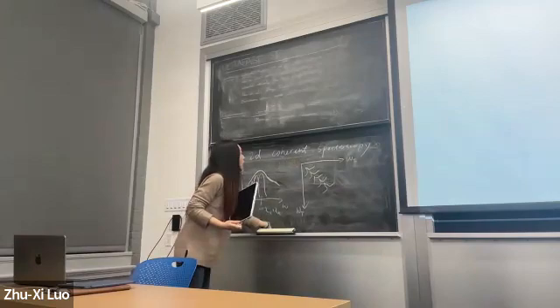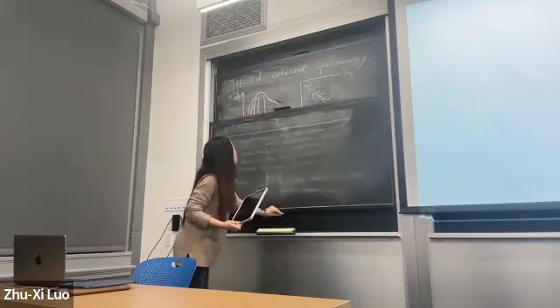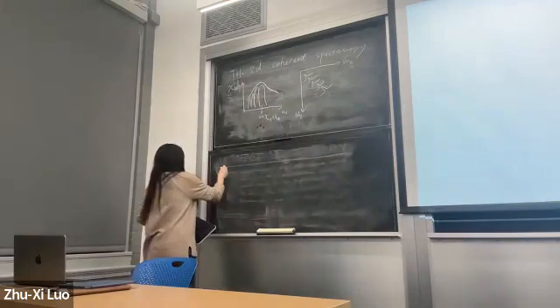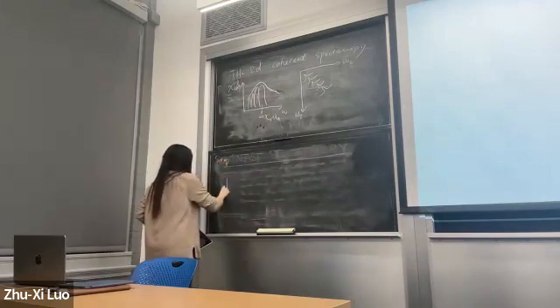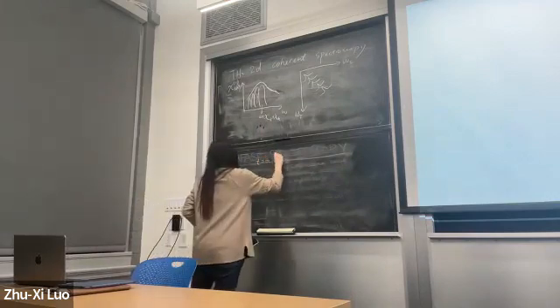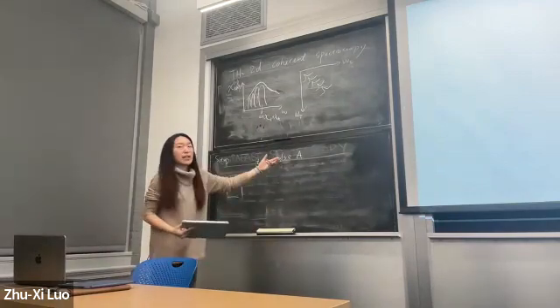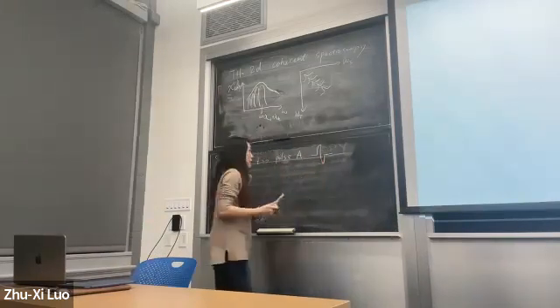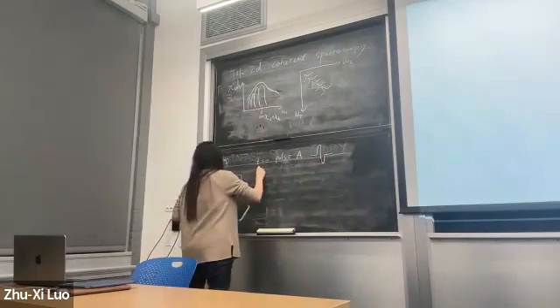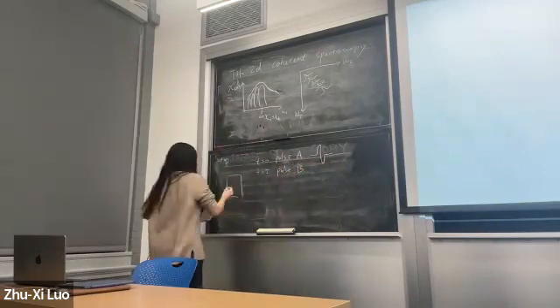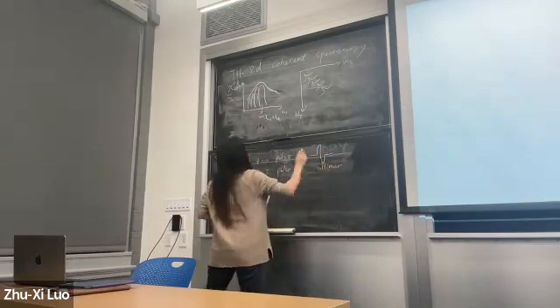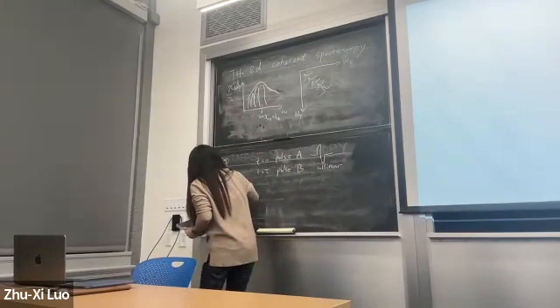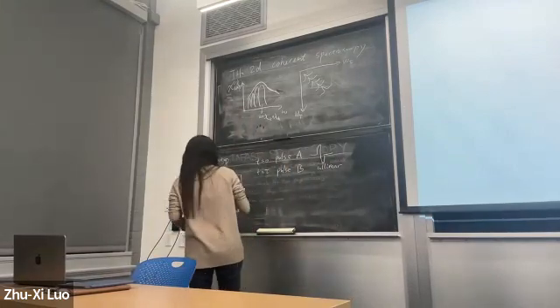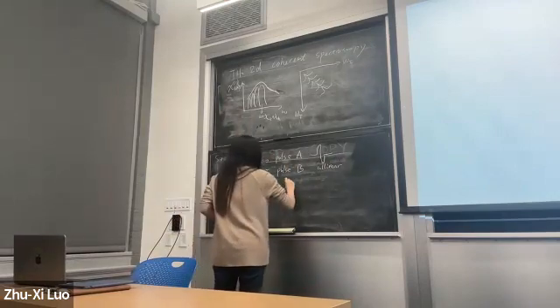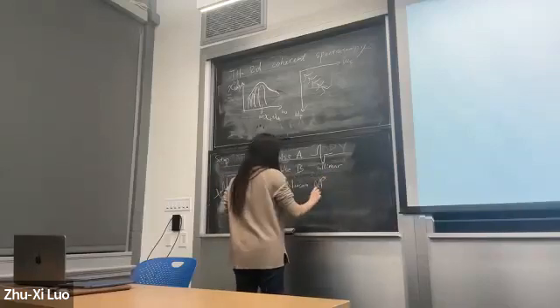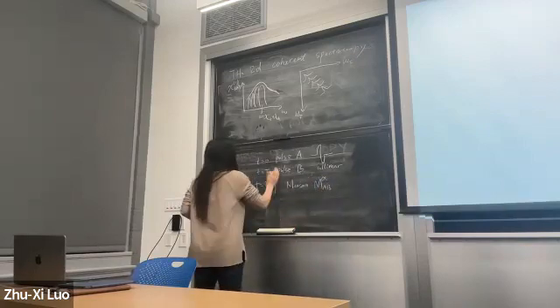Okay, so I'm going to discuss the setup of the paper. The setup is very simple. You have your sample here. At time t equals 0, you have a pulse A, single cycle, so you have just one period, and the period is like a picosecond. At t equals tau, you have your pulse B, which is collinear with pulse A. That's why we say the spectroscopy is coherent. So you have some delay. And then after that, at t equals tau plus t, you measure the magnetization in direction alpha due to the effect of pulses A and B.